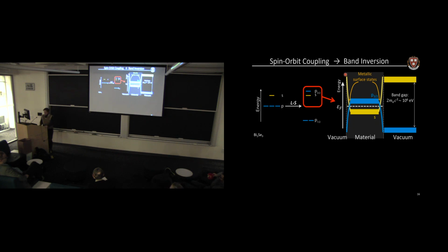And so at the edge of the material, we have conducting metallic states that pass through the Fermi level of the material. So this is what makes our chocolate bar uneatable, that no matter what we do, at the edge, there's always going to be a conducting surface state. Even if we break it, it will immediately have a conducting surface state on the new boundary of the material because of this topological requirement.